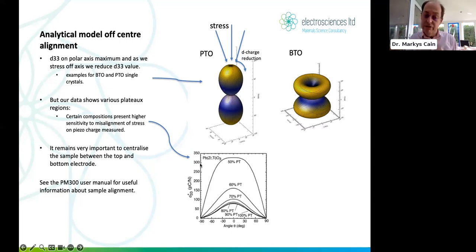Beautiful work of d33 against angle. This angle of force going from 0 to 90, 0 to minus 90, like this, and for different compositions of PZT. Now, a lot of people say, yeah, but even 10, 20 degrees off axis with a 50% PT, in other words, the composition of PZT, the value is fairly constant, it's fairly static. It should not be sensitive to misorientation in the way we've shown it. But we've seen sensitivity, haven't we? We've seen massive sensitivity to the way it's being held.